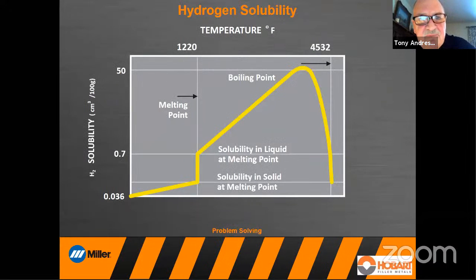This is a classic graph of the solubility of hydrogen in aluminum. As you can see at room temperature, it doesn't want anything to do with hydrogen, but as we get to its melting point, all of a sudden, at its melting point, 1220, its capacity to absorb hydrogen goes up tremendously and keeps going up as the temperature gets higher. So we're operating at temperatures around here somewhere, aren't we? 3,000 degrees, I don't know. Doesn't really matter. When we melt aluminum, it wants to suck in hydrogen. If there's any around the weld in various forms, it's going to take it on board. Then as the weld solidifies, it can't get out quick enough and it causes those bubbles right in the weld.